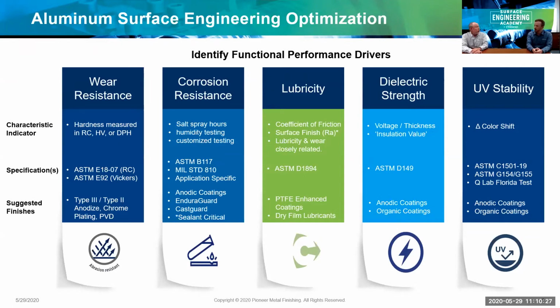So you can also provide different coatings that will make the part slippery for lubricity, a combination of a smooth finish and then also something that's naturally slippery. PTFE type materials do a great job. We've got anodized coatings that incorporate the PTFE. We've also got coatings that are plated that have co-deposition of PTFE, electroless nickel coatings, for example.